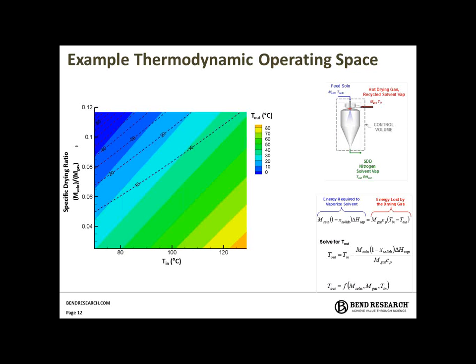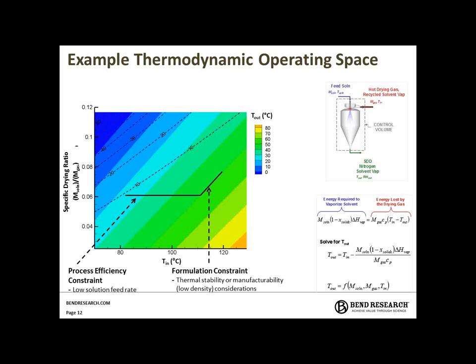Additionally, using those same mass and energy balances, you can overlay relative humidity contours on this plot. So some of the constraints we can overlay might simply just be a process efficiency constraint. So what's the minimum flow rate we'd want to run at with a given dryer scale to where the run times and cost of goods and efficiency make sense, or it could even be a solution stability constraint, identified early on in the process. The second constraint shown in this example follows an outlet temperature contour.